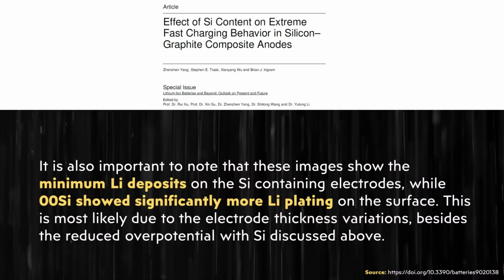So with that in mind, this is actually supported by these findings, where it's written here in this research paper, quote, "It is also important to note that these images show the minimum lithium deposits on the silicon-containing electrodes, while the 00Si, referring to the battery that had 0% silicon in the anode, showed significantly more lithium plating on the surface." And then once again, as I described, it's written here, quote, "This is most likely due to the electrode thickness variations besides the reduced overpotential with silicon discussed above."